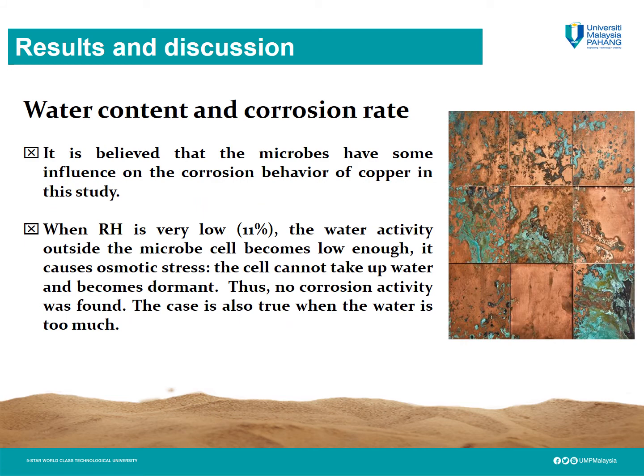It is believed that the microbe has some influence on the corrosion behavior of copper in this study. When relative humidity is low, the water activity outside the microbe cell becomes low enough that it causes osmotic stress. Thus, the cell cannot take up water and becomes dormant. Thus, no corrosion activity was found. The case is also true when the water content is too much.